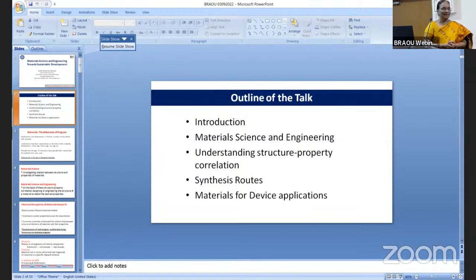Band gap is something we as physicists know cannot change. We know the band gap of silicon is 1.1 and germanium 0.8, but you cannot change it. But by making these kinds of hierarchical structures, we can actually play with the band gap. So those materials which are not functioning in the visible region, we can make them work in the visible region also. And of course, the advantage here is when you make these kinds of stacked heterostructures, you also reduce the recombination. Recombination is basically when you shine light and you create electron hole pairs, the first probability is they recombine.